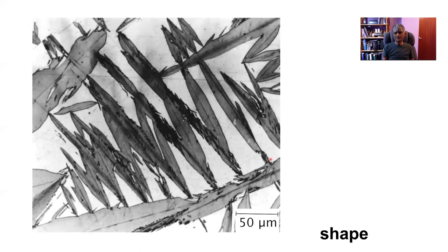Now, this is a nice optical micrograph. If you look at the scale here, this is an optical micrograph illustrating the shape of martensite. Now, the obvious conclusion to jump from this is that these are actually needles of martensite inside the matrix of austenite here. But you would be wrong, because you're looking at two-dimensional sections. These are plates in three dimensions. You can prove that by looking at the plates on a two surface analysis. So you metallographically polish two surfaces sharing a common edge, and then you can see that the actual three-dimensional shape is plate-like. Indeed, if it was needle-like, you'd see lots and lots of elliptical or round sections, which you never do. So martensite is definitely in the form of a plate.